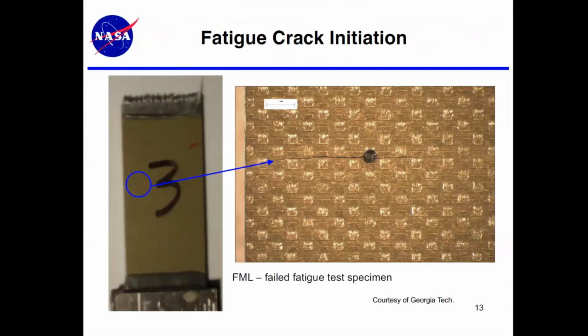The next chart shows a fiber metal laminate, FML, that was exposed to fatigue testing. You can see that the fatigue cracks do initiate around the holes within the material itself. So there is a reduction in fatigue properties. We went into the work understanding that there would be some reduction in fatigue, but we also realized there were a number of applications that weren't fatigue property driven, like blast containment, for example. So our focus really was on non-fatigue driven applications for these types of materials.